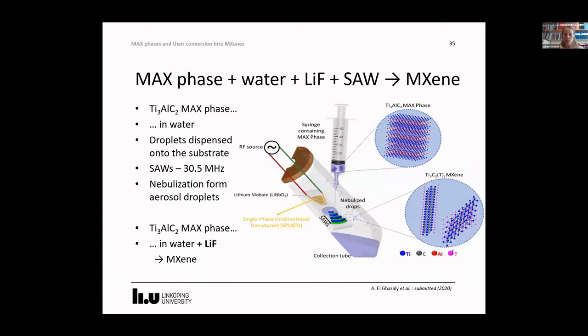The key is addition of lithium fluoride. In other words, if we have a MAX phase in water and lithium fluoride and then apply the surface acoustic waves, then the nebulized drops contain delaminated MXene flakes. How can this be explained?